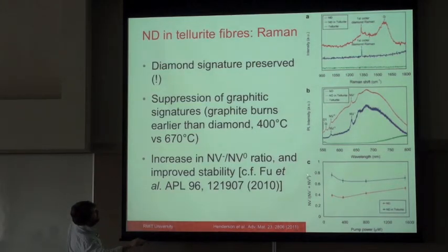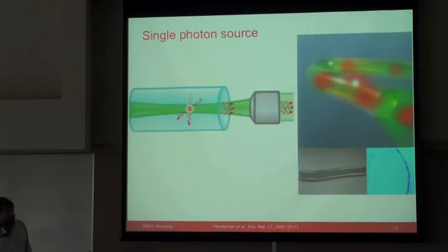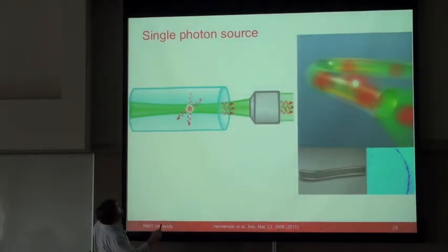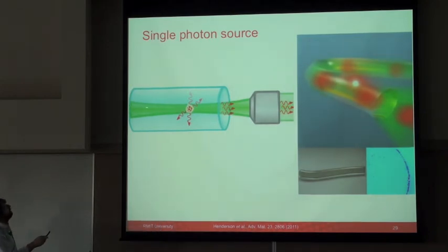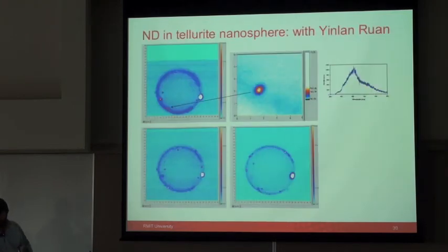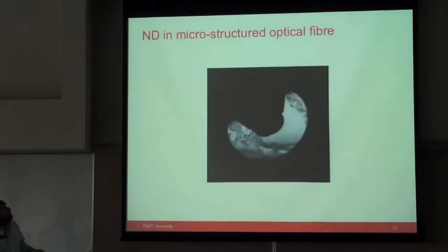And we're also seeing that the NV minus to NV0 ratio is improving, which we put down to the fact that we're oxygen terminating the surface. And this has been seen in bulk samples. The concept is that ultimately we want to be able to take these nanodiamonds and put them inside the core mode of a single mode optical fibre with very narrow core, so that we get preferential emission into the fibre mode, and then we can use that as a fibre-coupled single photon source. And we've been looking also at other structures. We're looking further at microstructured optical fibres.